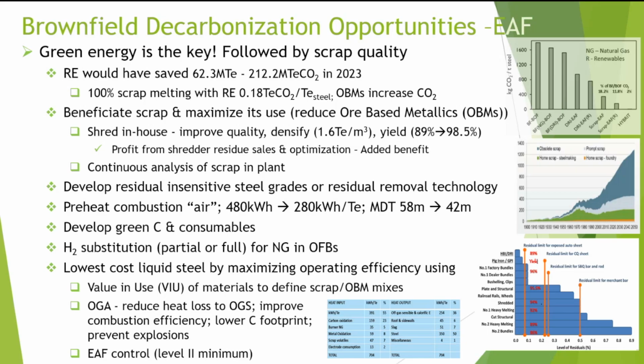Using preheat on the combustion air for the burners could also benefit the industry. In this particular case that I worked on, 480 kilowatts can be dropped to 280 if you do that, and you can drop meltdown time 16 minutes. Obviously, we need to develop the green carbon and consumables for use in the arc furnace. Hydrogen substitution, partial or fully, for the natural gas in the burners has already been worked on and is being tested in some of the plants.